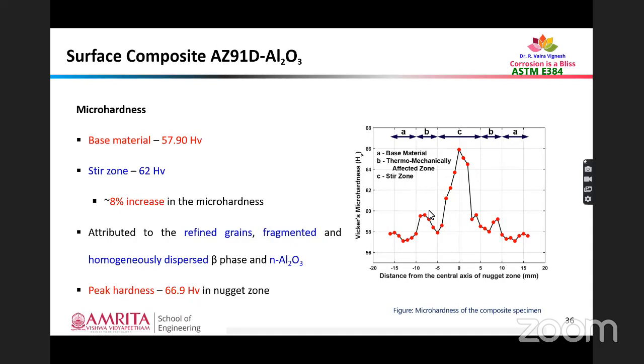So we can see the trend of microhardness. Obviously within the nugget zone, exactly at the middle part, the microhardness is much higher, and it reached around 66.9 HV. And in the TMAZ, because of the elongation of grains, the hardness was much more limited. And in the base material zone, it had an average hardness of 57.9 HV.